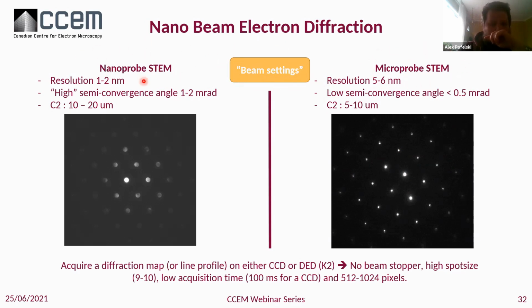The difference between these two modes is that you have a different convergence. So what you want is to have a STEM probe with disks that are not overlapping with each other. You want them to be isolated to be able to identify their position and measure the distances and angles between them. In those types of settings, usually what you want to look at is to have a small C2. That's the first thing that you're looking at. And then afterwards, depending on the microprobe and nanoprobe, you will have what we call the high semi-convergence angle in terms of strain, 1 to 2 milliradians, which is still very low, and the low semi-convergence angle in the microprobe, which is very small, less than 0.5 milliradians.